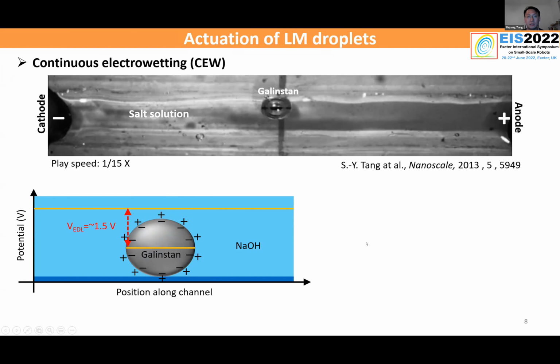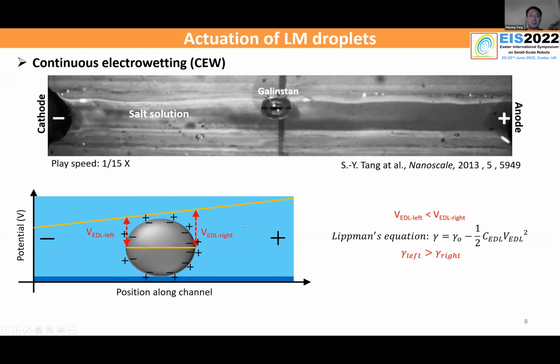And when you apply an external potential gradient, what it actually does is induce an imbalance of the voltage drop across this electrical double layer. Because the liquid metal itself is highly conductive, it will remain at equal potential, while the external potential gradient will form in the solution. So the right-hand side will have a high voltage drop across the EDL, while the left-hand side has a lower voltage drop. Based on the Lippmann equation, the surface tension is equal to the maximum surface tension without any electrical double layer minus the energy stored inside the capacitor formed by the electrical double layer. So the larger voltage drop means a lower interfacial tension.